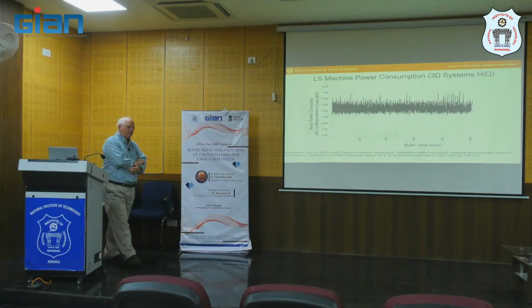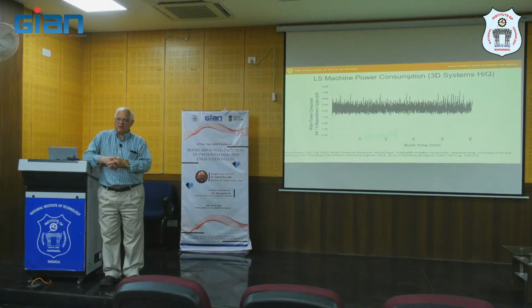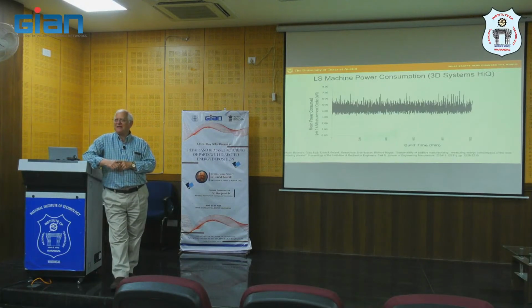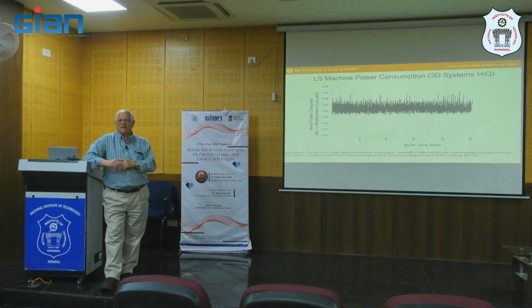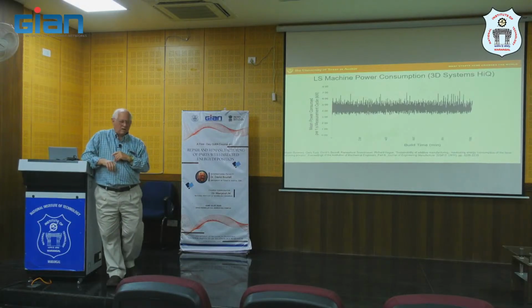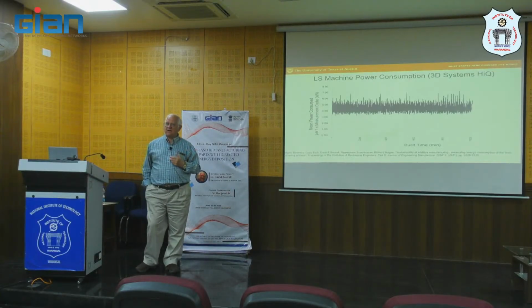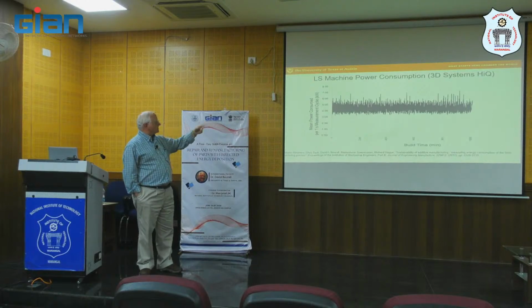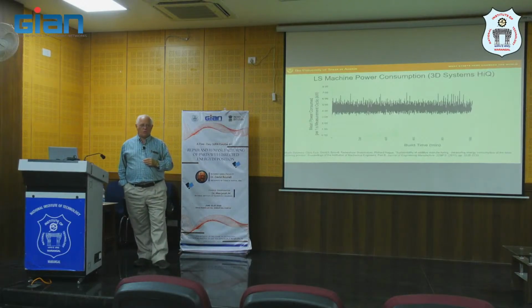Let me just give you an impression of what an energy analysis can look like. I looked around. I couldn't find anything on an energy analysis for DED, but I did have one. This is work that I did with the guys at Nottingham in the UK about 15 years ago, with powder bed fusion and with nylon. So we looked at nylon powder bed fusion, and what we see is that the machine, we were working with a 3D Systems HiQ machine, took about 4,500 watts to run.